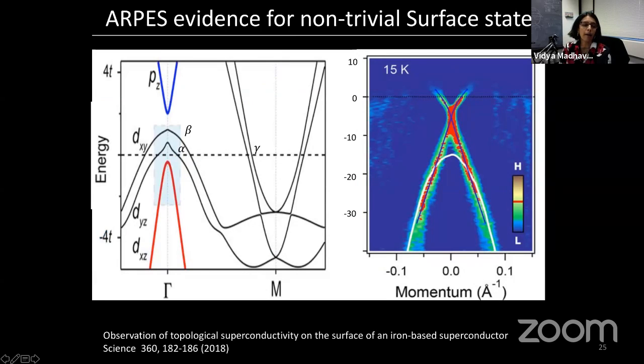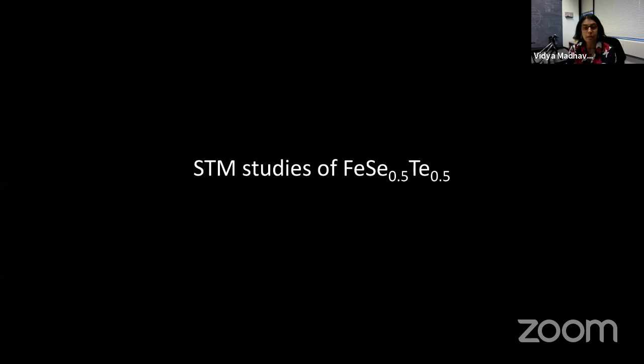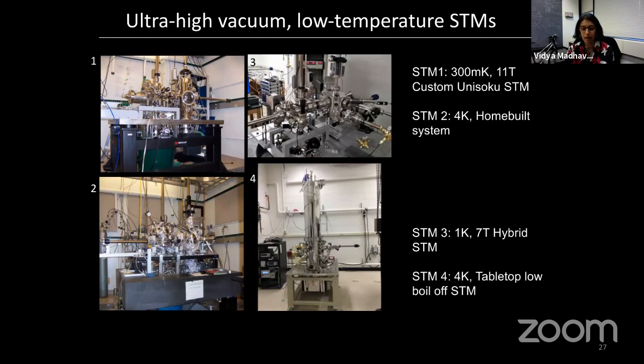So as a result of this band inversion, like I said, there should be surface states inside the gap. And in fact, ARPES studies showed the existence of these linearly dispersing surface states in this gap, right at this energy, close to the Fermi energy. And so this is an ideal system in which, all in one system, you have a proximatized topological system. It's not an insulator; it's a metal, but you have a proximatized topologically non-trivial system.